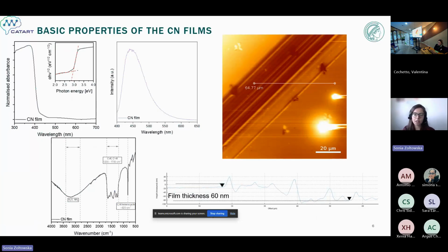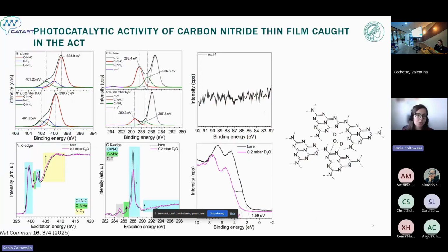And those samples then were used to perform operando atmospheric pressure XPS characterization during the flow of heavy water to perform the water splitting reaction. But here on the top, you can see the typical XPS spectra of the carbon nitride film. You can also see the valence band XPS showing that the HOMO level is around 1.6 electronvolts, which is typical for the carbon nitride film in ultra high vacuum conditions. But what happened when we flow the heavy water into the system? We use a pressure of 0.2 millibar.